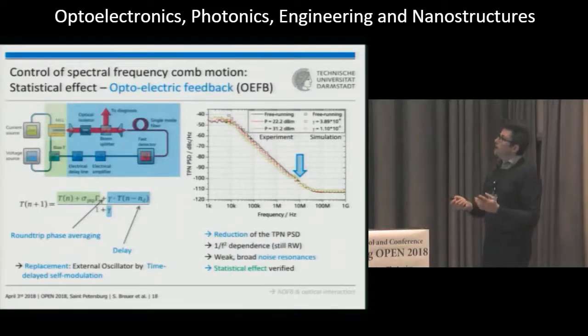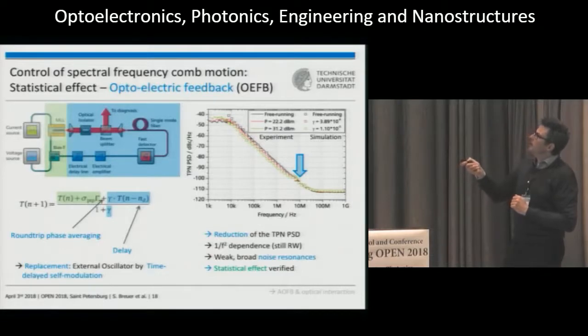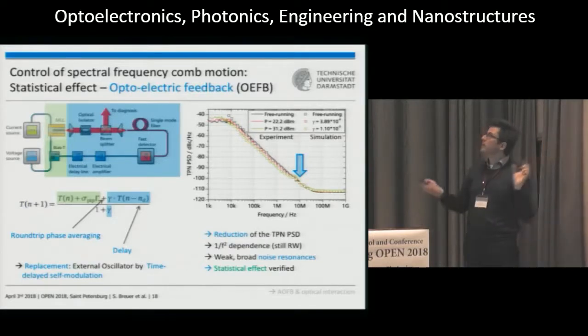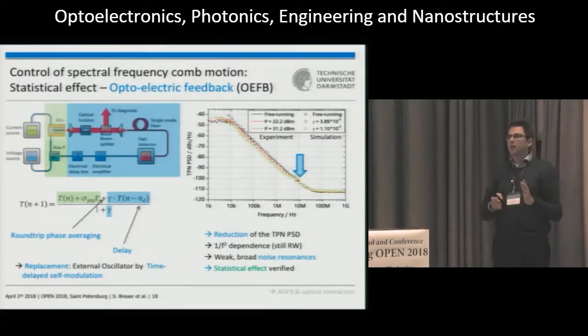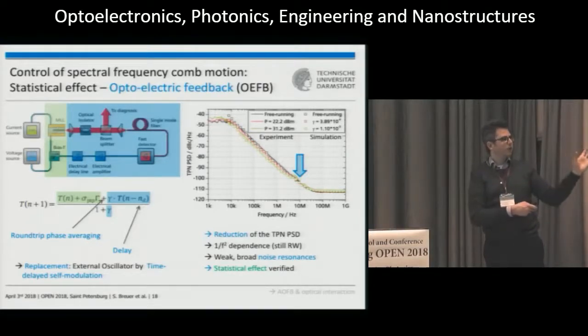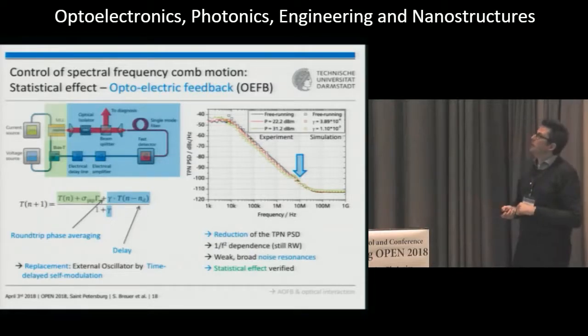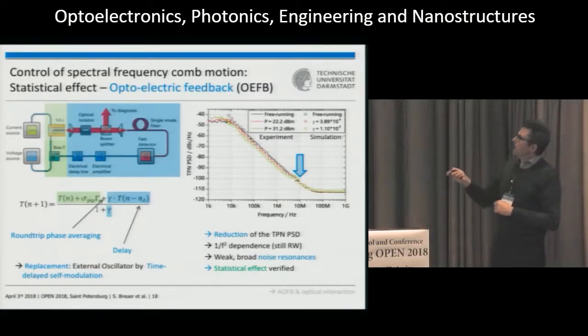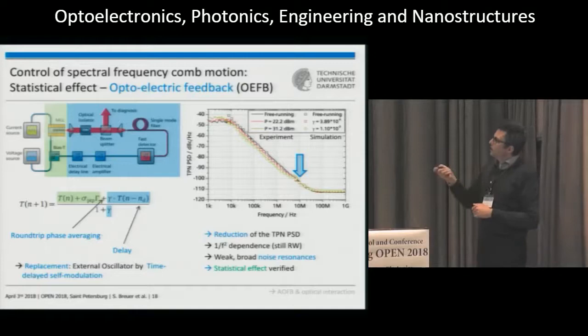Before we do that, we look at a combination of opto-electrical feedback. In this case, we collect the light, send it through a fiber, detect the light, and then pick out the fundamental repetition rate, the comb spacing frequency, and inject it via a bias T back into the absorber section. For example, an 8 millimeter long laser with 5 gigahertz is an ideal laser for this experiment. You have 5 gigahertz electrically that can be conveniently detected and injected back into the laser. In that case, we have to include a round-trip phase averaging term and the delay term of this external cavity.